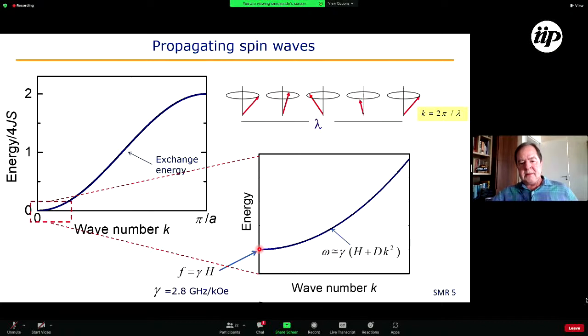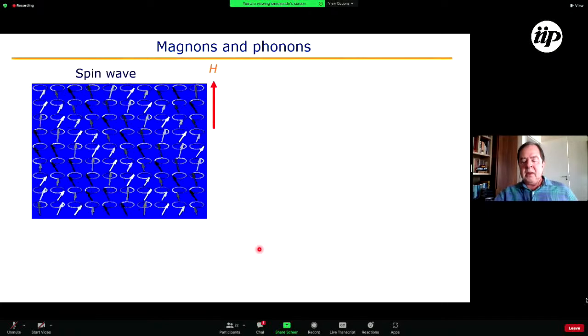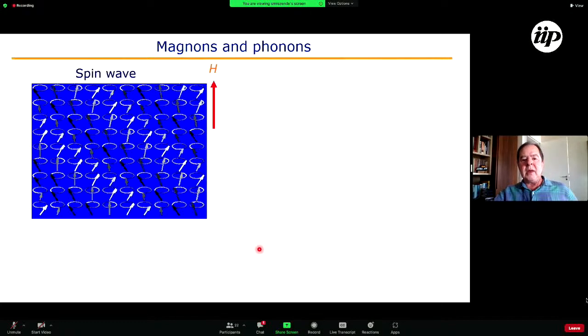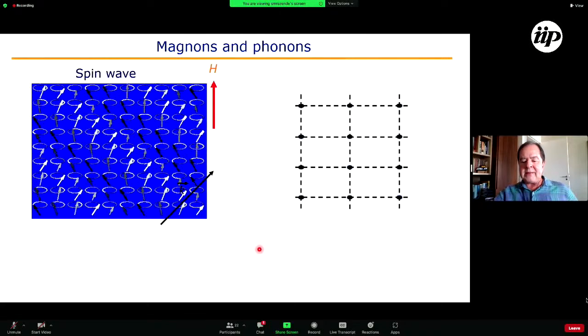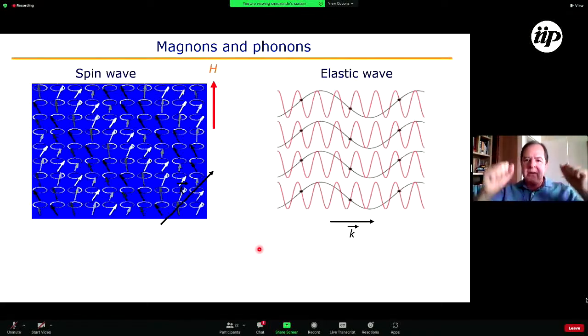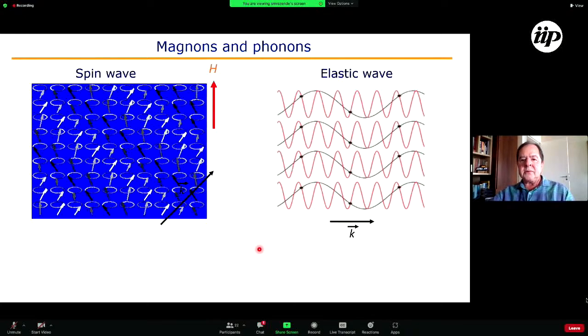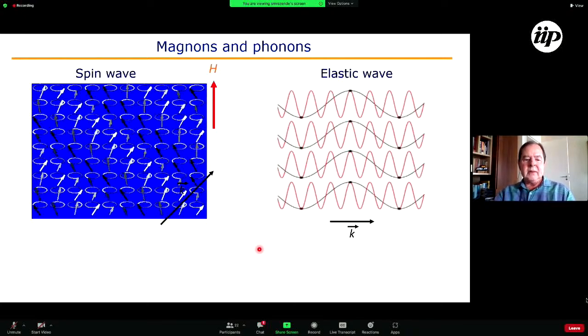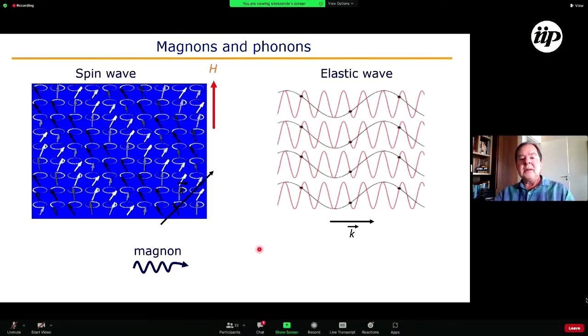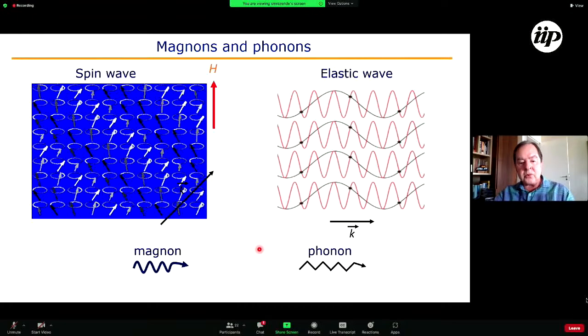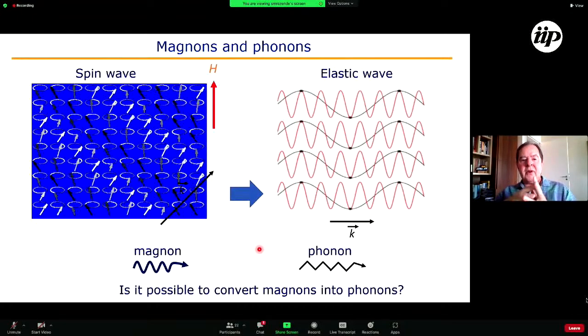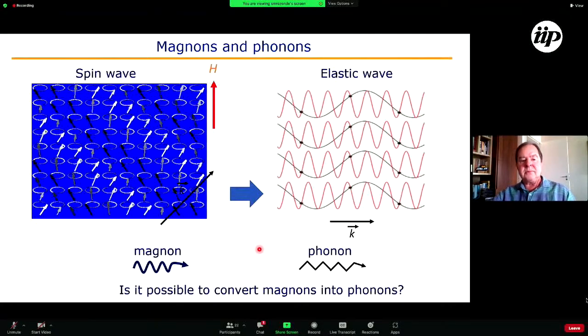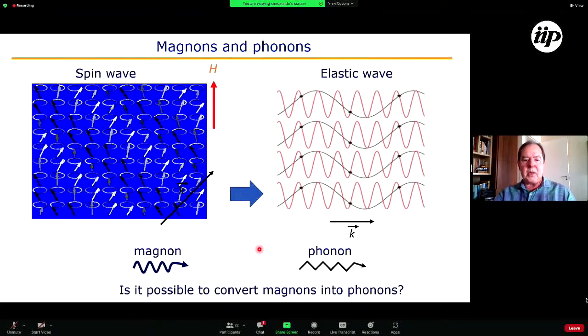And this is important for the first experiments I'm going to show, because one can excite spin waves with a microwave field. Now, as I said, this is a view of a spin wave, and this is a simple view of an elastic wave in a solid. The vibration of the atoms, the ions, is an elastic wave. The quanta of spin waves are called magnons. The quanta of elastic waves are called phonons. And one asks, is it possible in a ferromagnetic material to convert magnons into phonons? I'll show shortly that this is indeed possible.